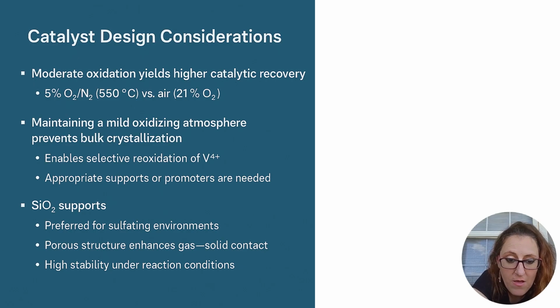Non-uniform loading, by contrast, can cause localized crystallization, hinder redox flexibility, and accelerate deactivation. Silica's chemical inertness and structural stability make it superior to supports such as titanium dioxide or zirconium dioxide, which tend to form sulfates or degrade under sulfur trioxide and sulfuric acid vapors.